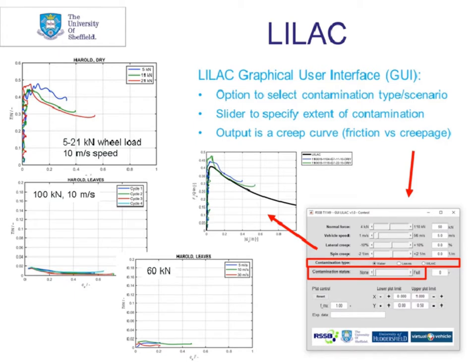This data was used to parameterize a model using the LILAC approach. You can see the graphical user interface through it here. So you can put in wheel-rail interface conditions, contamination type and amount, and then you can output a creep curve, as is shown in the middle graph. So this can be integrated with, for example, a multi-body dynamic simulation. So you can assess how train performance is affected by having those low adhesion conditions.